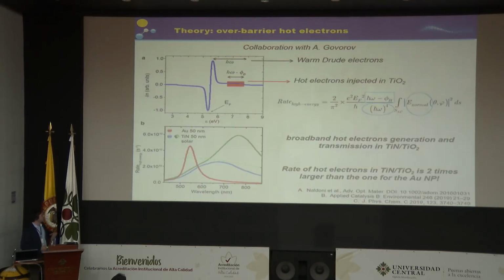Anyhow, titanium nitride has also been used in other photoelectrochemical devices. Recently, currents much higher than what we reported have been reported, going up to 4 milliamps, and so this starts to be really interesting for real devices that should have at least 10 milliamps per square centimeter to deploy some kind of device which can return the investment made for the development of the devices.